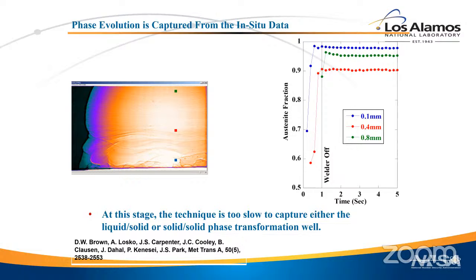Now, when we did this measurement in 2017 or so, the fastest detector could only read at about a 10 hertz rate. So that was limiting on how fast we could collect data. And when we did these experiments, more than really trying to understand stainless steel, we were trying to understand the technique and how far you could push the technique.